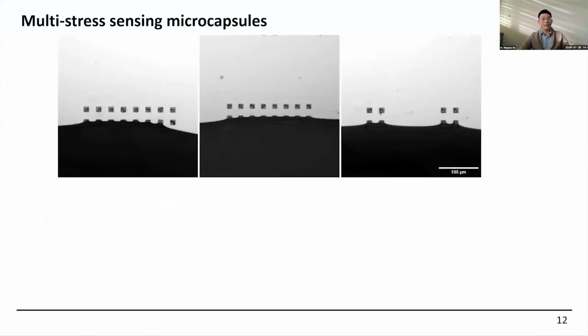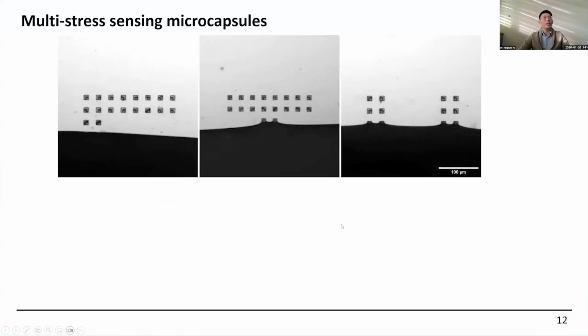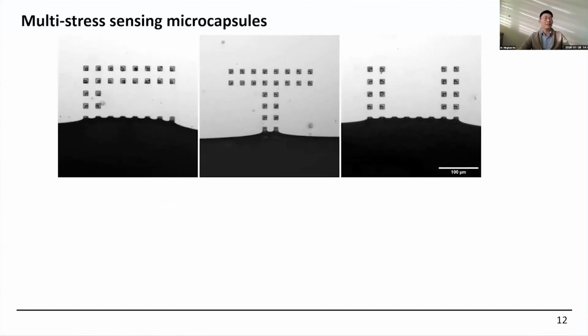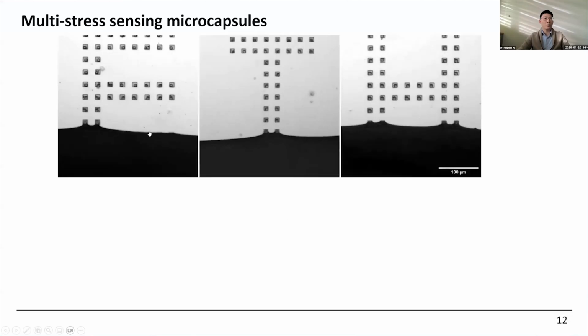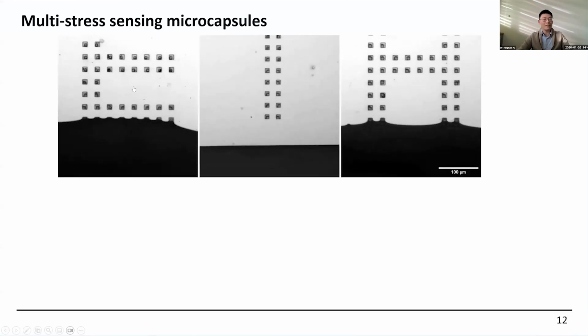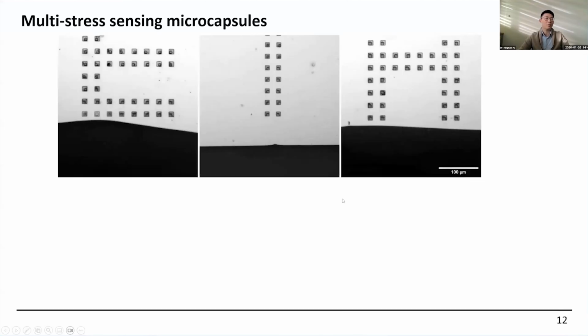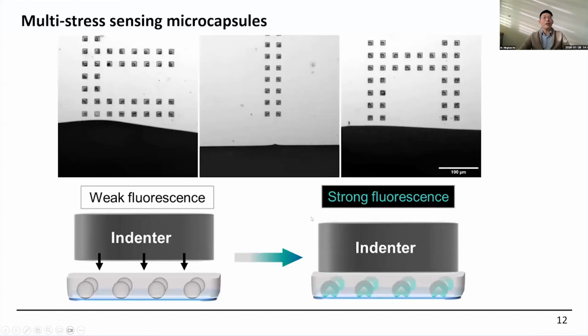And the next step would be to test if they can really translate this mechanical signal into this optical signal. So to do that, first we put these different microcapsules with the dye inside these different patterns. Since we are at ETH, we just put it into the ETH letters. And then once we apply the different force, the microcapsule should be broken to show the strong fluorescent color.